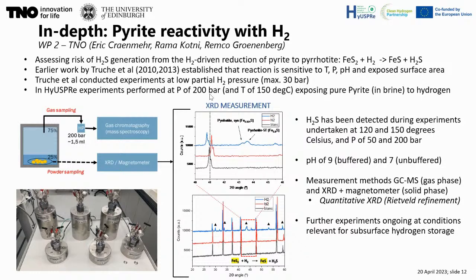This is still underway, so we only have intermediate results here, but on the left you see the setup, exposing pure pyrite submerged in brine with a headspace of hydrogen atmosphere, sampling at regular intervals, measuring with GCMS, XRD, and/or magnetometer, and powder sampling post-mortem. And what we found so far is that we do indeed see the reaction ongoing at 120 and 150 degrees and a pressure of 50 and 200 bar hydrogen. This is also at the pH of 9, so that's a pH-buffered solution and an unbuffered solution.